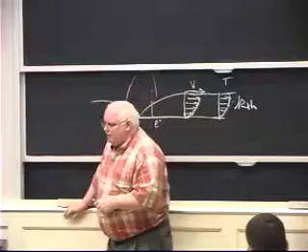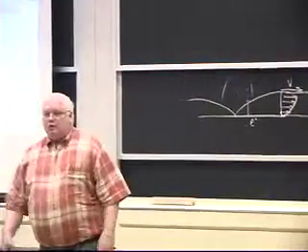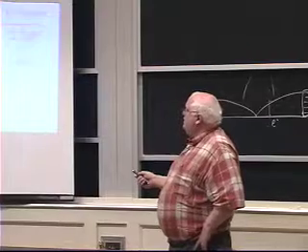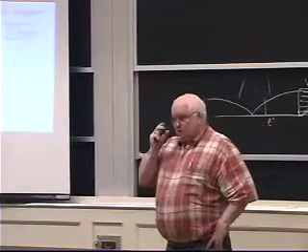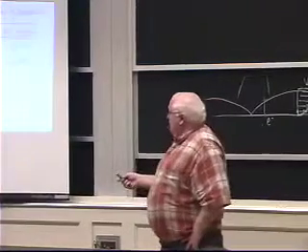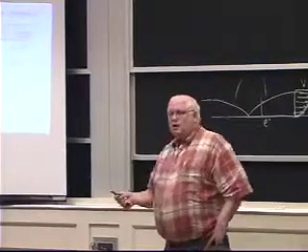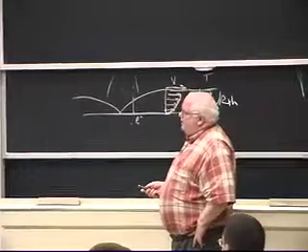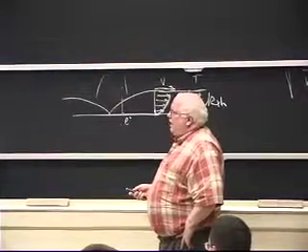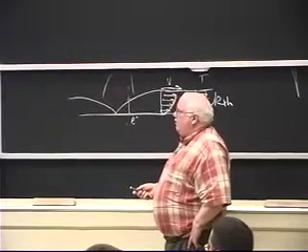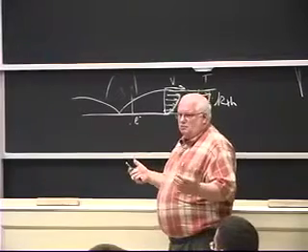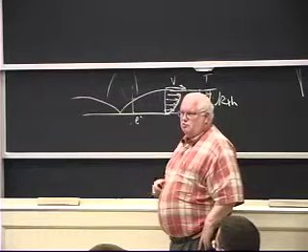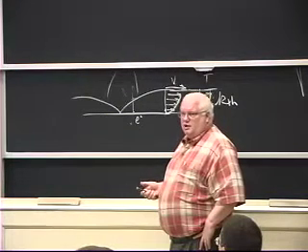Now this is a total variance with the Welding Handbook. The Welding Handbook will tell you that argon has an ionization potential of 15, and helium has an ionization potential of 24 volts, and therefore it takes more energy to ionize the helium, and therefore it gives you a hotter arc. The problem with that is if you make mixtures of argon and helium, you don't find that that's true. You don't have a hotter arc in terms of degrees Kelvin.